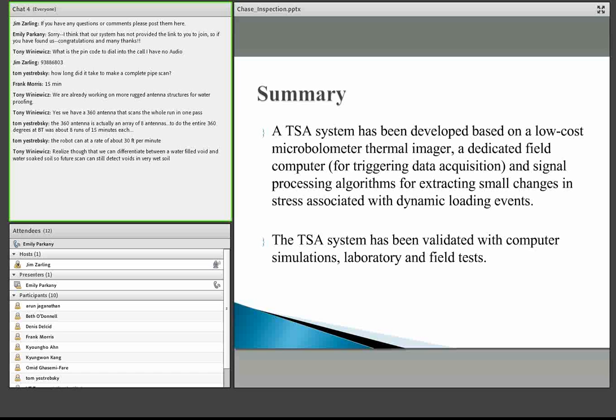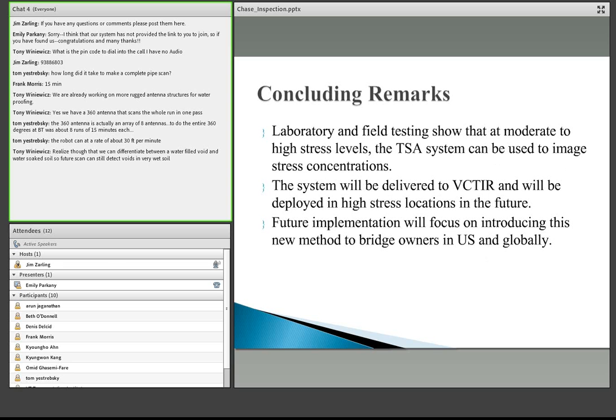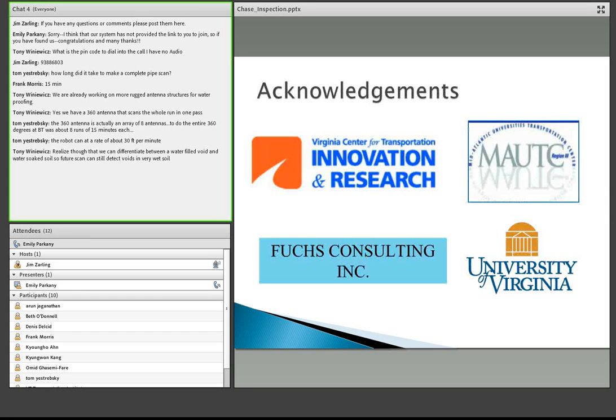We have demonstrated that we have developed and are to be delivering this system to the Virginia Department of Transportation at the end of this month. We have validated its ability to detect fatigue cracks and measure stress concentrations in the laboratory and in the field. We do plan to try to interest other DOTs and bridge owners in this technology, but this technology is also applicable to any dynamically loaded structure, particularly structures made out of metal because they have a very strong thermoelastic signal, but also because they're prone to fatigue.